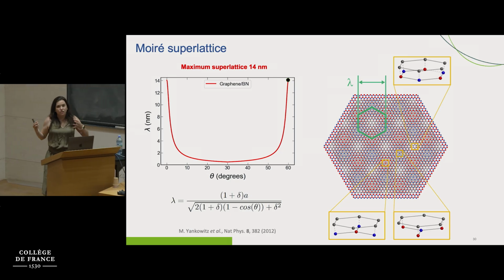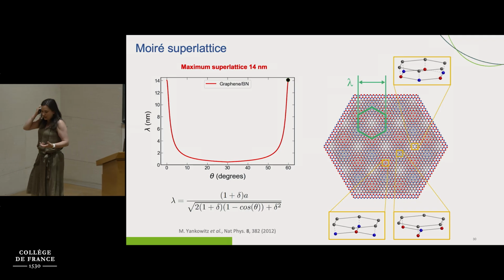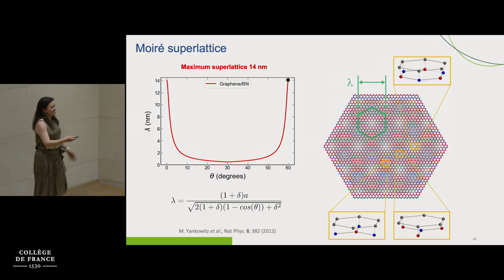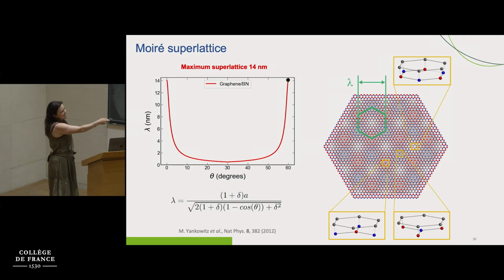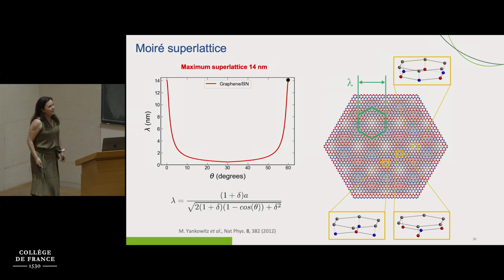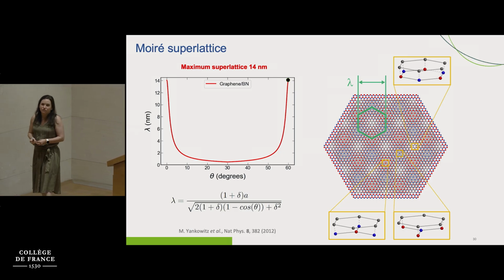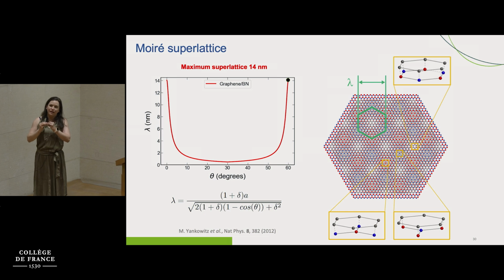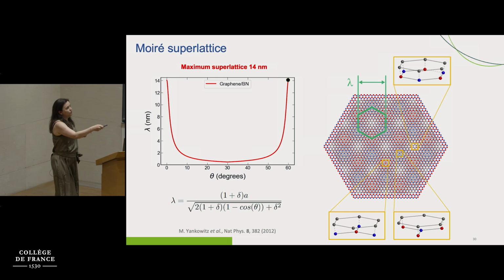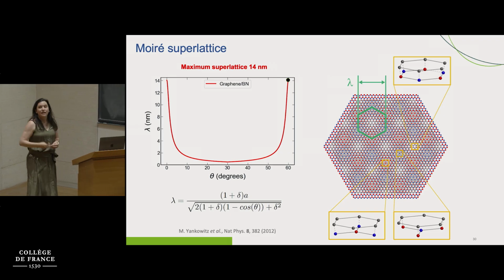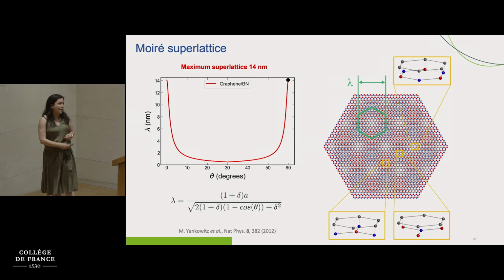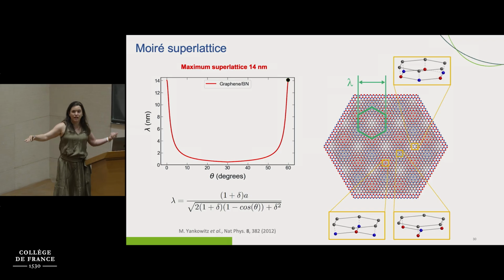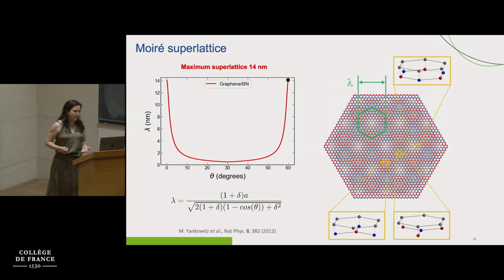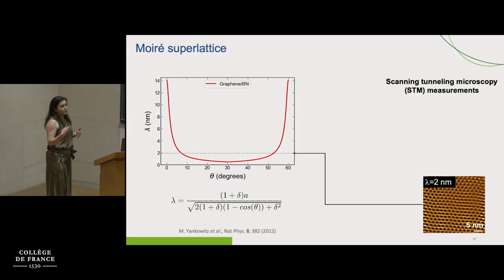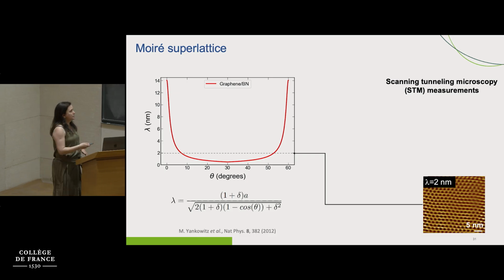But what's the origin of this? This is just an effect of who is near you, in fact. You can see in these three spots that we picked that the moiré effect is just related to the fact that not every carbon atom is going to have the same environment. However, another carbon atom at a certain distance called lambda is going to have the same environment. This creates a periodic modulation of the landscape. This has been observed in STM measurements for a long time.